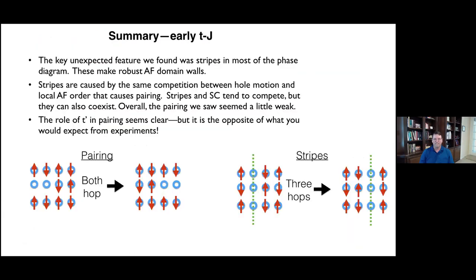So let me summarize. The summary from the early TJ results is that there's a key unexpected feature we found: stripes were present in most of the phase diagram. These stripes make robust antiferromagnetic domain walls. The stripes are caused by the same competition between hole motion and local antiferromagnetic order that causes pairing.